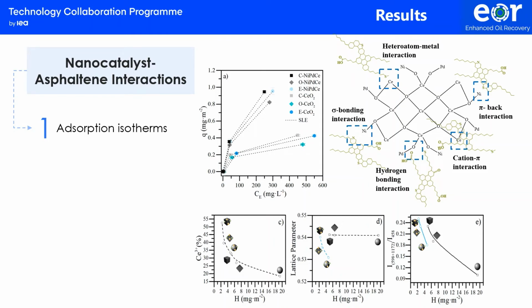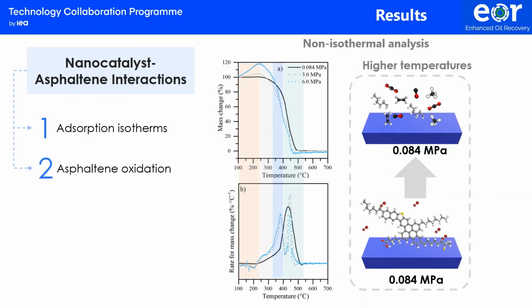For the oxidation experiments, this figure shows that the asphaltenes without nanoparticles decompose entirely up to 500 degrees Celsius at 0.084 megapascals.